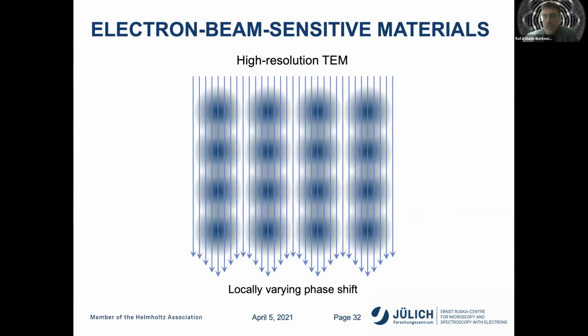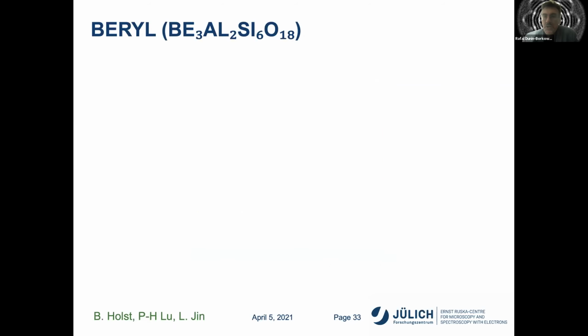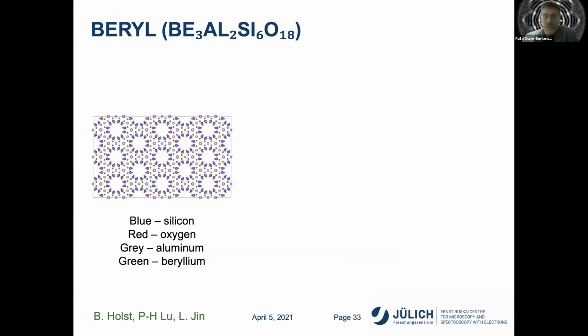If we look at electron beam sensitive materials, we are also interested in dose efficiency of these techniques. And here I'd like to illustrate the imaging of a very beam sensitive mineral sample. This is Beryl, beryllium, aluminium, silicon oxide. This is work carried out in cooperation with Bodil Holst from Bergen in Norway. And this particular structure has channels inside it. And not only channels, but it has individual atomic columns that comprise beryllium atoms, which are very weakly scattering, and the entire structure is very beam sensitive.